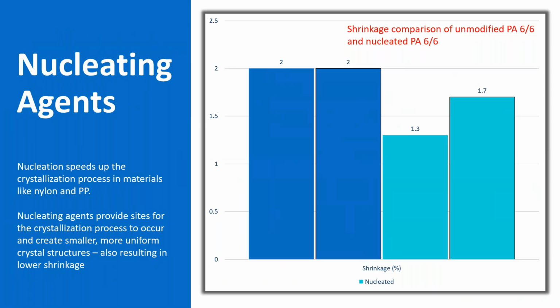And so that's presented here comparing an unmodified 6,6, so no nucleating agent in it. It shrinks at 2% or 20 thou inch per inch, compared to basically the same 6,6, except we've added in a bunch of nucleating agent to it. And so the shrinkage is now only 1.3 and 1.7. So it drops your shrinkage down as well. And so when we think about the example I gave with carbon black, maybe your carbon black nylon shrunk a little less than the natural version.